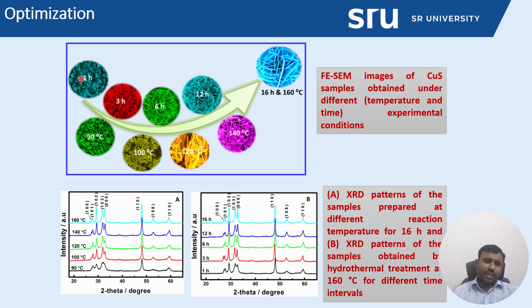At 1 hour, an irregular or spherical morphology has been observed. When increasing time, the spherical morphology slowly develops into some sheet-like morphology. Followed by, when increasing the time further up to 12 hours, we are getting the highly flower-like morphology. So it indicates that a minimum of 15 to 16 hours is required to achieve a highly uniform flower-like morphology. When increasing the time further, the morphology does not change. So we have optimized 16 hours as a sufficient time to form a well-defined flower-like morphology.